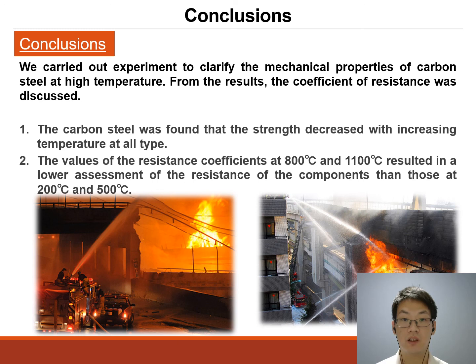First, it was found that the strength of carbon steel decreased with increasing temperature at all times. Next, the values of the resistance coefficients at 800 degrees and 1100 degrees resulted in a lower assessment of the resistance of the component than those at 200 degrees and 500 degrees.